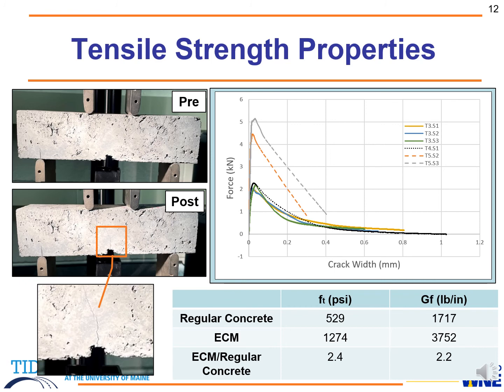So for fracture energy, in terms of pounds per inch, regular concrete was right around 1,717, where ECM came in at 3,752. This is right around 2.2 times greater than regular concrete.